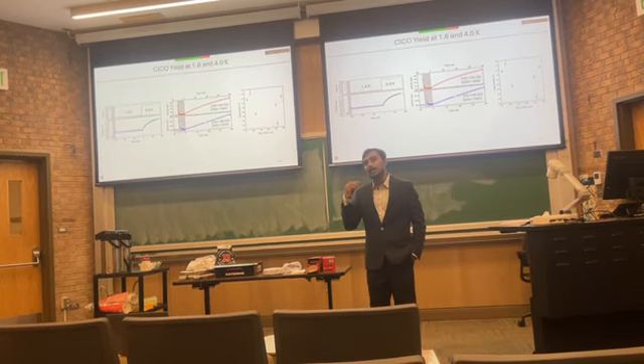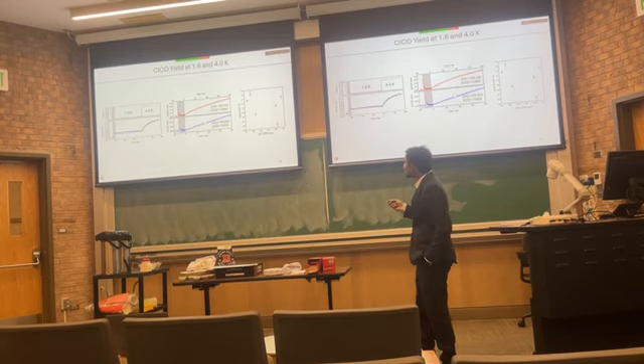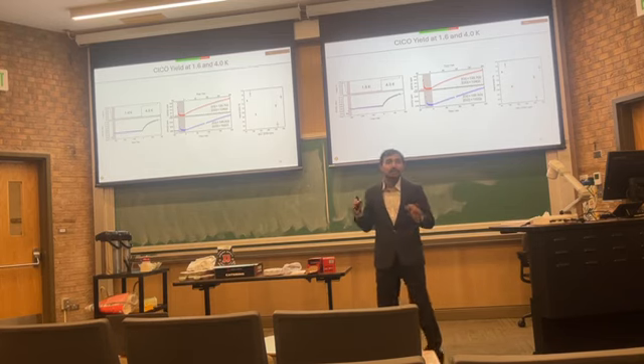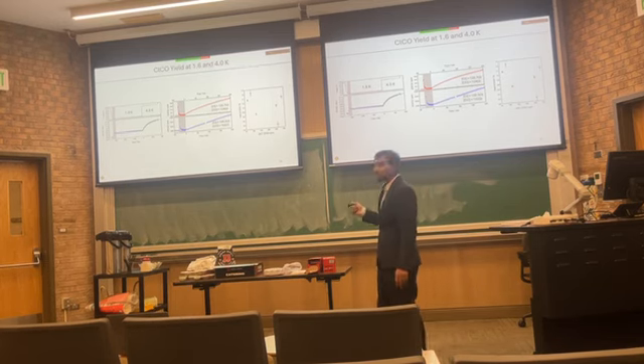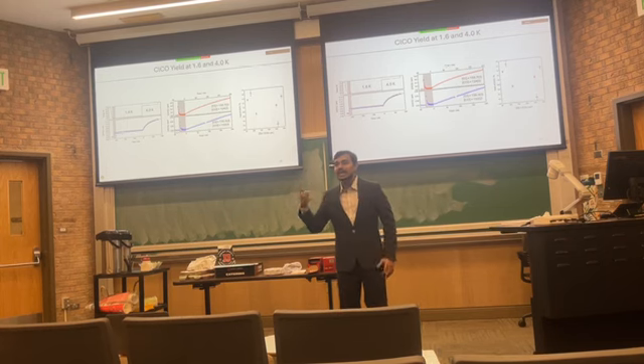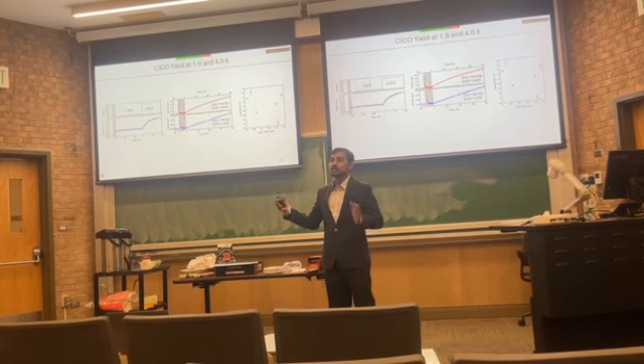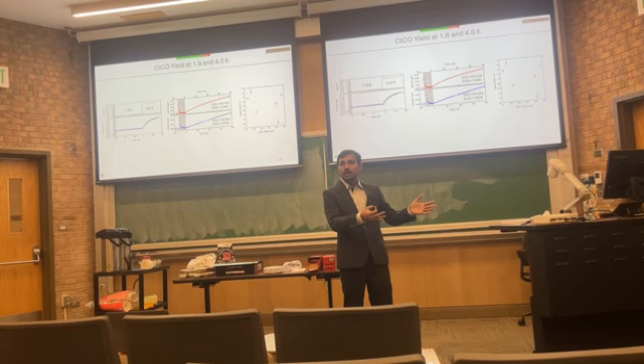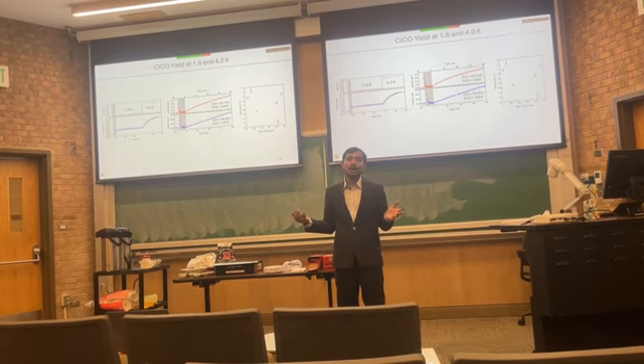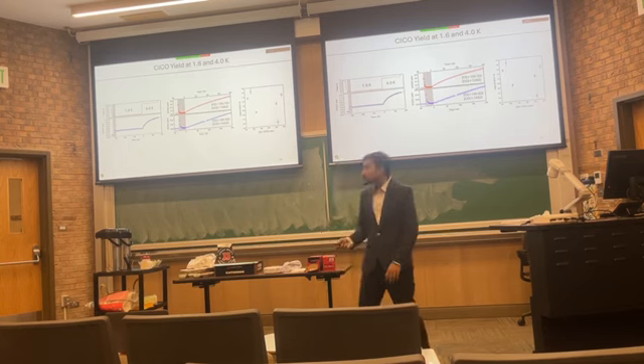The question to ask is, why is there only 1.2% yield at 4 Kelvin, or only 0.1% at low temperature? Because we have the other 98.8% chlorine left inside the system. We have carbon monoxide. Why are they not reacting? We don't know the answer to that question.